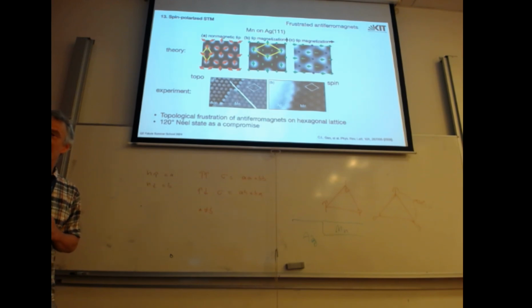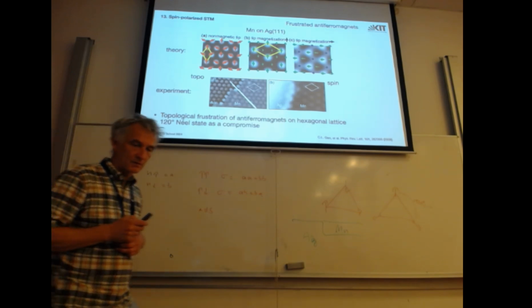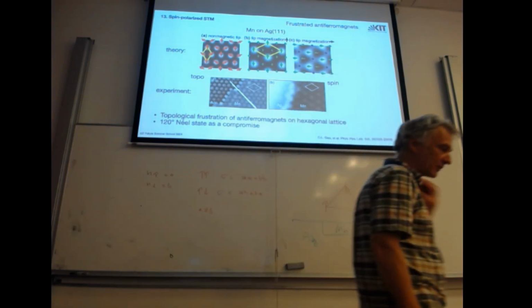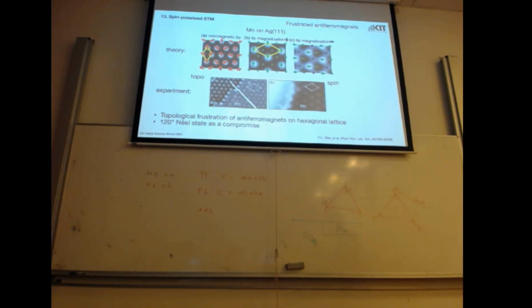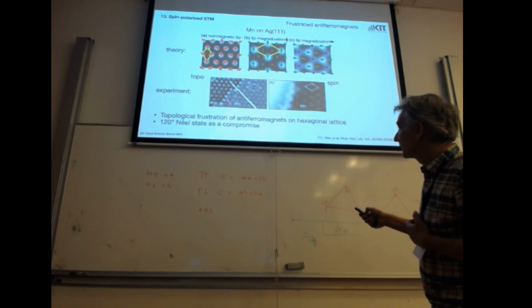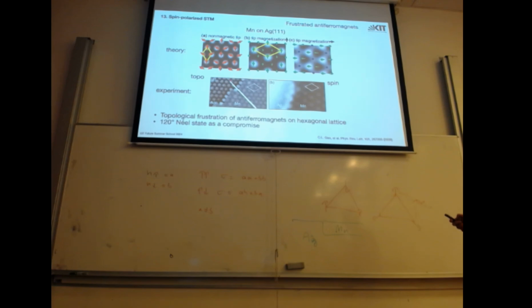Just to make sure I understood the concept correctly. In the second picture, what you do is you consider the difference in signals between tip that's polarized in this direction and this direction, and because you know that you're searching for AFM pattern for Néel ordering, you will expect bumps in the material where there is such polarization, and this bump has particular texture, and in still where there's no texture whatsoever, that's why it's just a uniform background. Yeah, so here is principally the situation of unpolarized tip, which is the square of the electron wave function. And here we also see the square of the electron wave function, separately for spin up, spin down, and weighted by the tip polarization. So B is a difference between the two polarizations, or is this the direct image? So it's particular polarization. Okay.